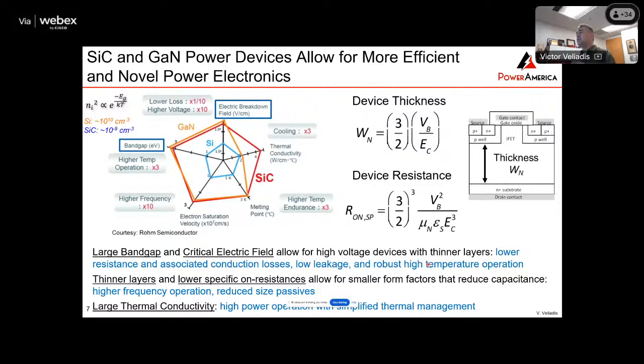So the fact that you have a thinner layer for the same voltage capability means that you have low resistance and therefore lower conduction losses. The fact that you have the large band gap, as I mentioned before, means that your leakage is very low at room temperature, very few carriers excited. And also, it means that you can operate at higher temperatures. And the fact that you now have thinner layers and lower resistance means that you have a smaller form factor that reduces capacitance. And this is critical because it means you can operate at higher frequency, which minimizes the size of the passive components like the inductors and the capacitors and the transformers.